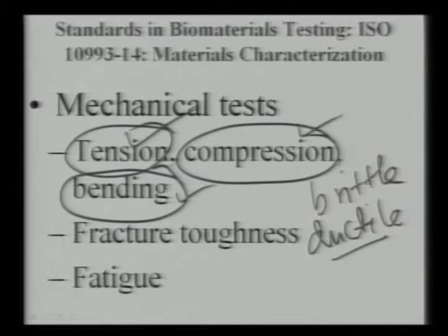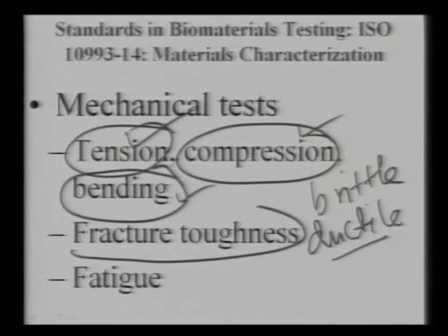Okay, and accordingly you can calculate the elastic modulus, the strength, the ultimate tensile strength, etc. You can measure the fracture toughness. This toughness can be measured from the simple tensile test from the area under the curve, or the fracture toughness of ceramics can be measured by the single edge V-notch beam, or by putting in an indentation, measuring the crack length, and so on, and adopting certain equations.